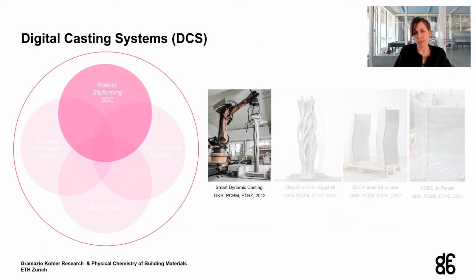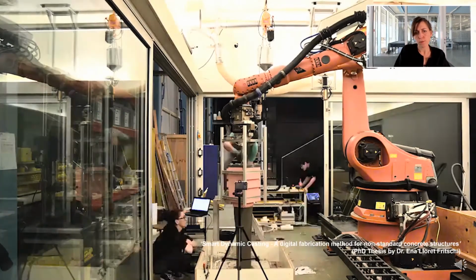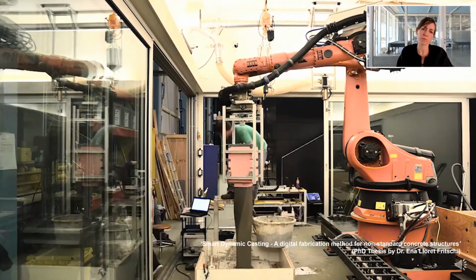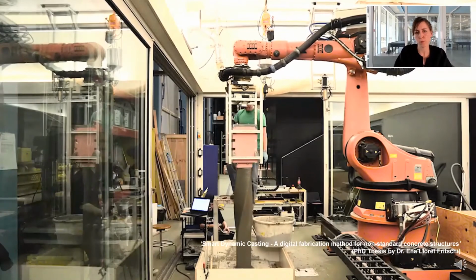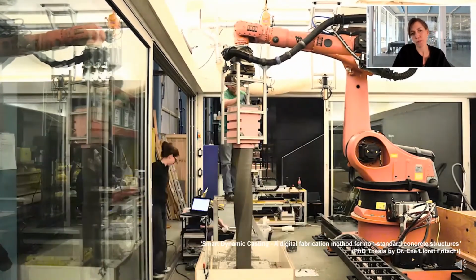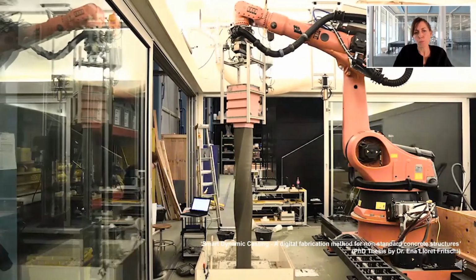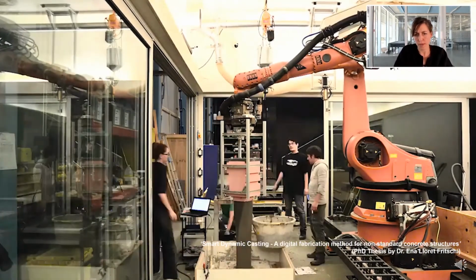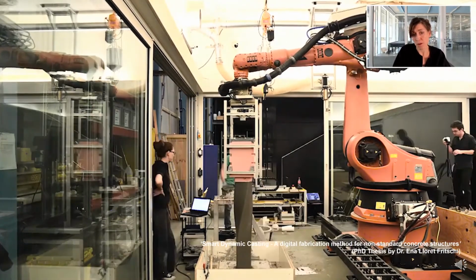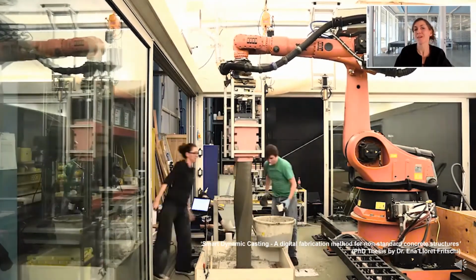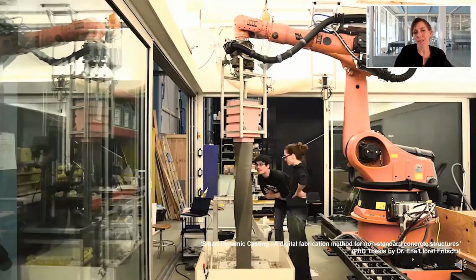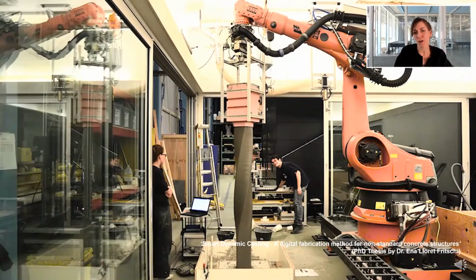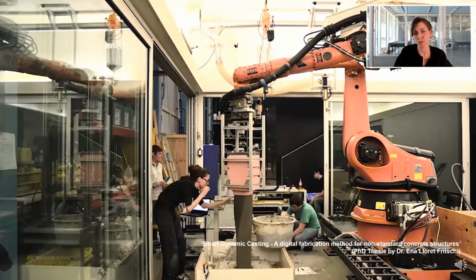I will start to present smart dynamic casting to give you a first overview of how the process works. This video is one of the first videos taken of a successful production of a column, which proves that it's possible to shape concrete when it changes from a soft to a hard material. It's worth noticing that at that point in time we had a retarded mix in a bucket, and then we accelerated it manually with a stirring stick and placed it into the formwork at a rate set by the hydration of the concrete, which we measured offline on the digital penetrometer, which you see in the background.